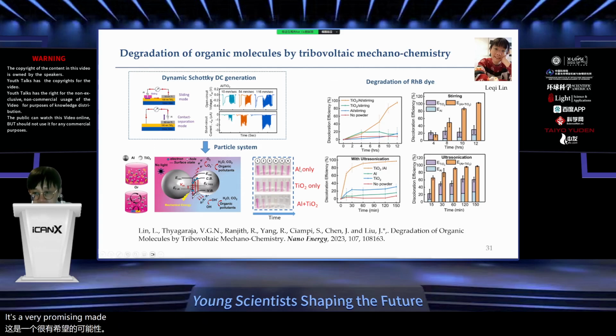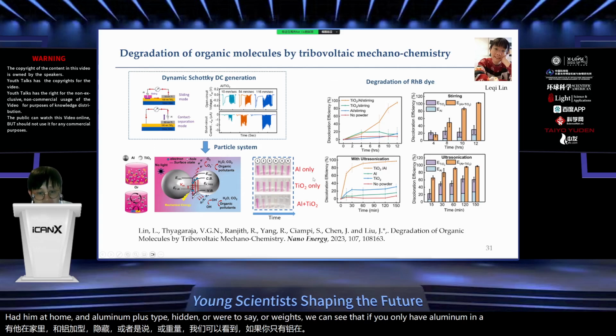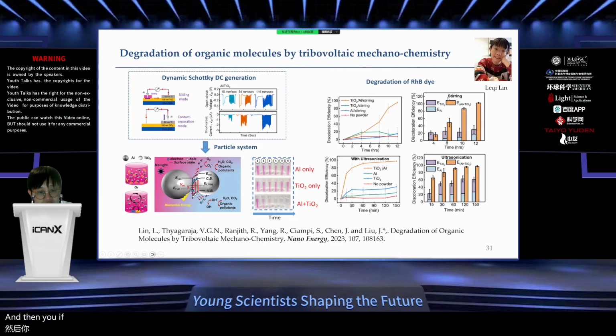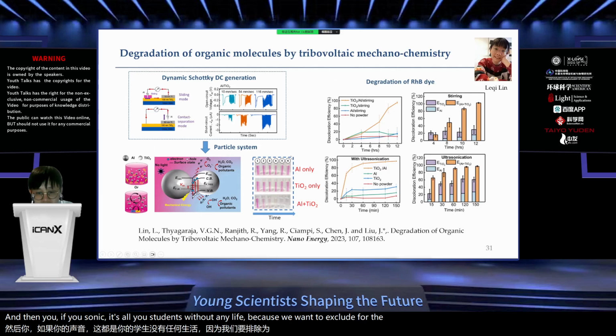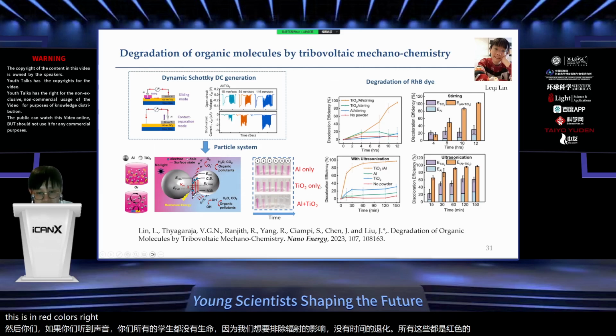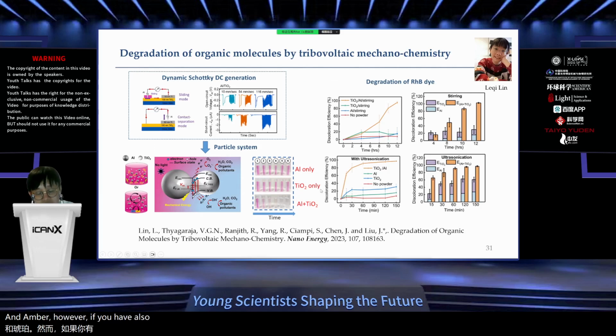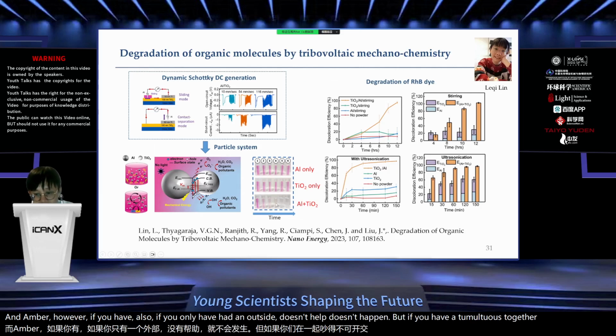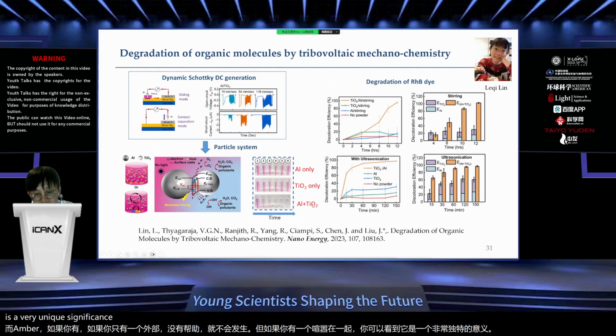Now you can see that we have aluminum only, titanium oxide only, and aluminum plus titanium oxide, with the same weights. If you only have aluminum in a solution, and you sonicate or stir it without any light, because we want to exclude the irradiation effects, there's no degradation of these dye molecules. This is in red color, right? And if you only have titanium oxide, it doesn't happen. But if you have the two materials together, you can see a very significant degradation of these organic molecules, which is very exciting.